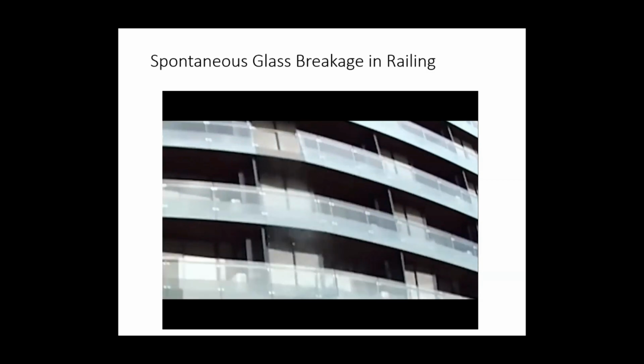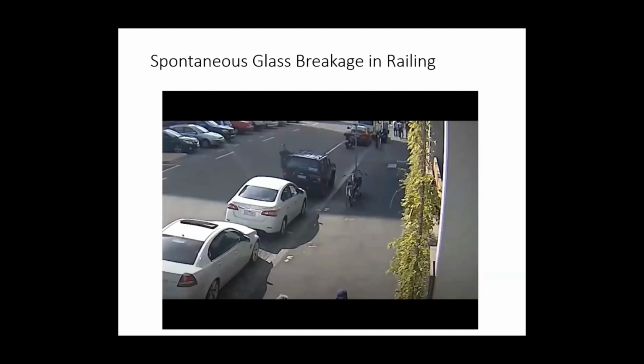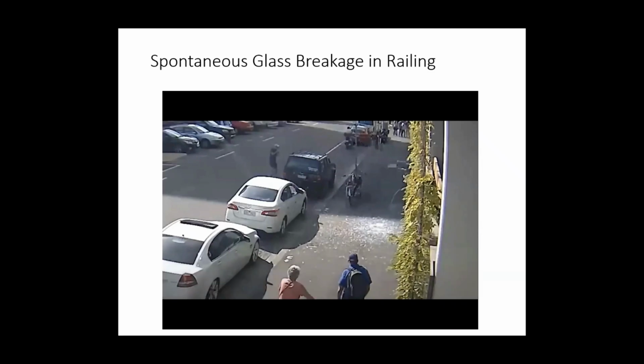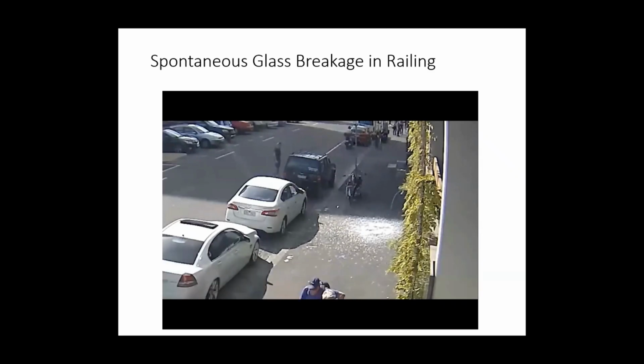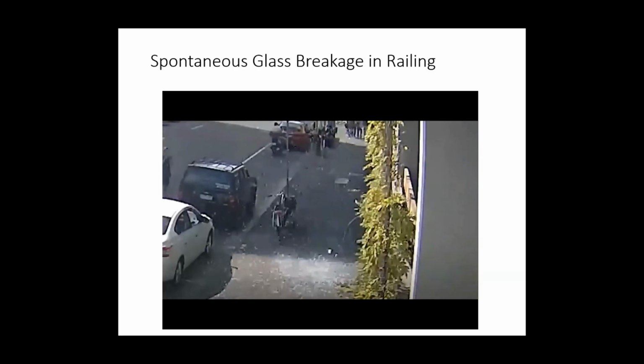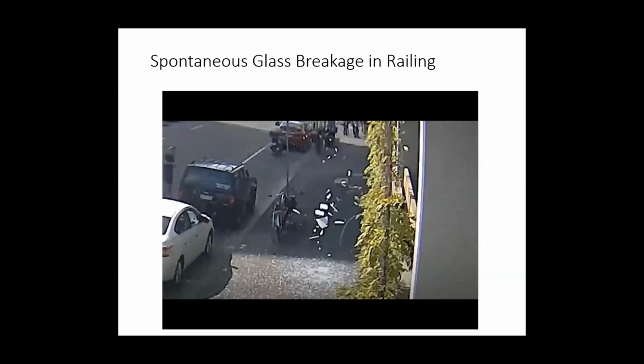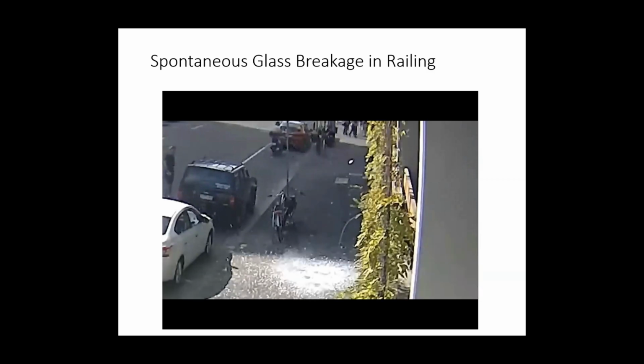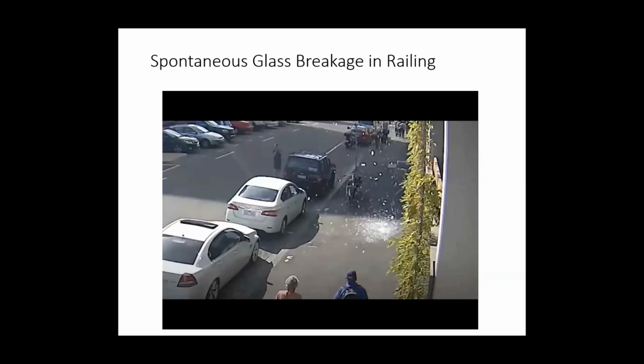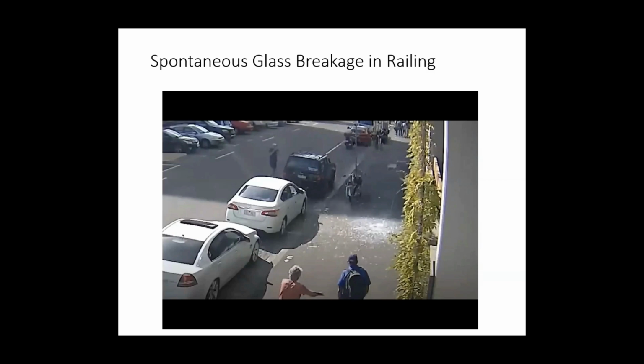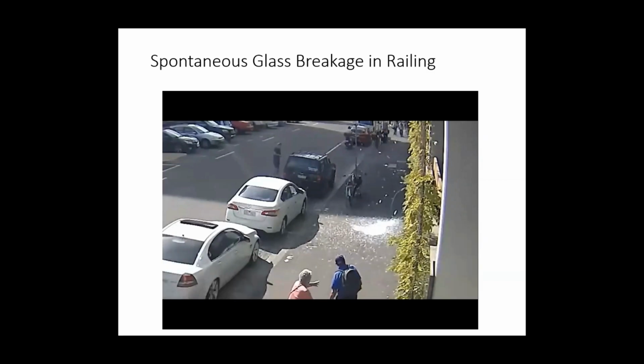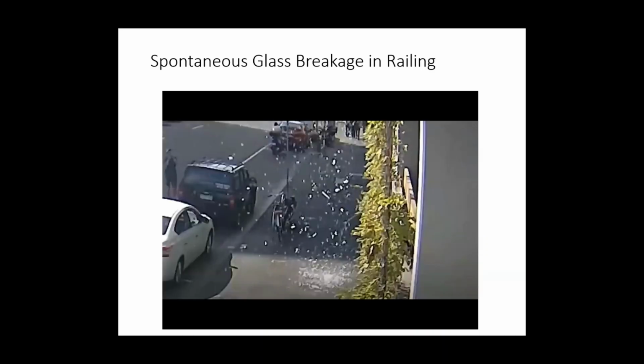Now there is something called nickel sulfide inclusion. It is an impurity that's sometimes in the glass, and when the glass is tempered, it can spontaneously break if there's too much of this nickel sulfide inclusion in there. One way of preventing this, it's not guaranteed, but you can heat soak the glass after you temper it. But this is one reason why glass railings are now laminated instead of tempered.